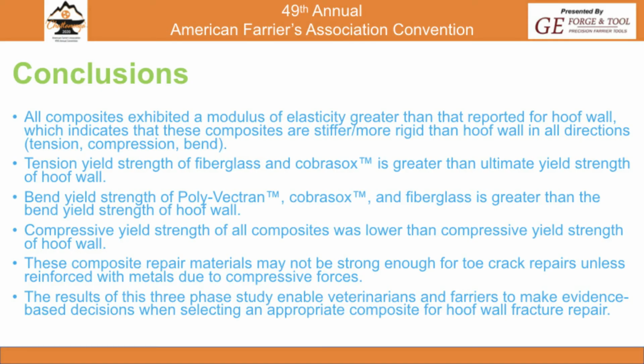And so again, all composites exhibited a modulus of elasticity greater than what's reported for hoof wall, which indicates these composites are stiffer or more rigid than hoof wall in all directions, meaning tension, compression, and bend. Yet the tension yield strength of fiberglass and Cobra stocks is greater than the ultimate yield strength of hoof wall. The bend yield strength of polyvectran, Cobra stocks, and fiberglass are all greater than the bend yield strength for hoof wall. But unfortunately, compressive yield strength for all of these composites was lower than the compressive yield strength for hoof wall, which again I think is what makes them susceptible when we start repairing toe cracks with them.